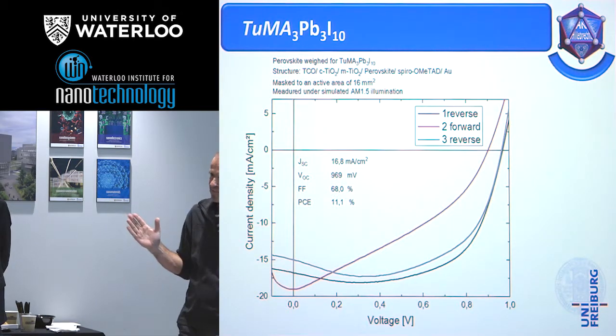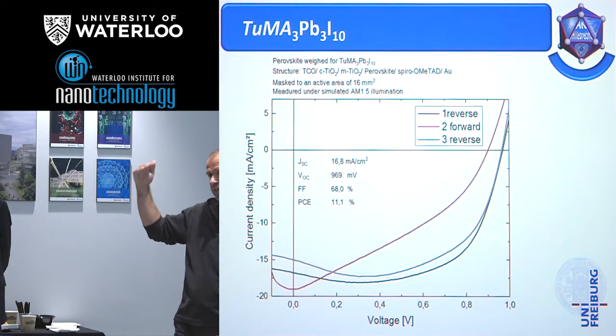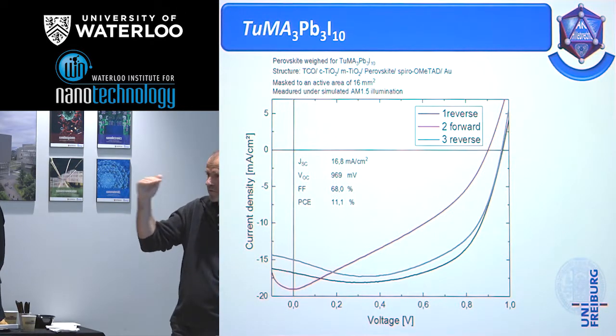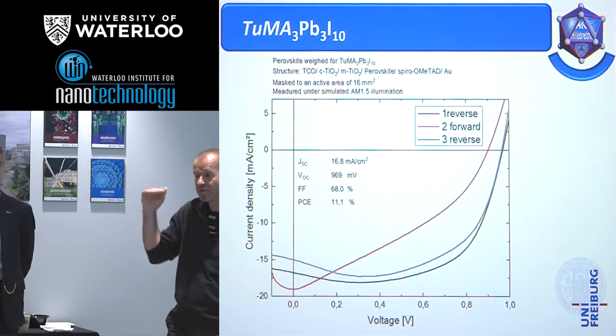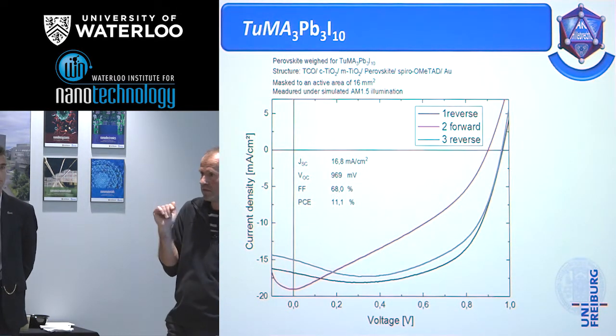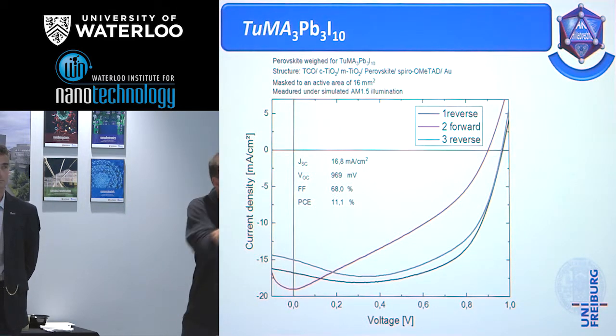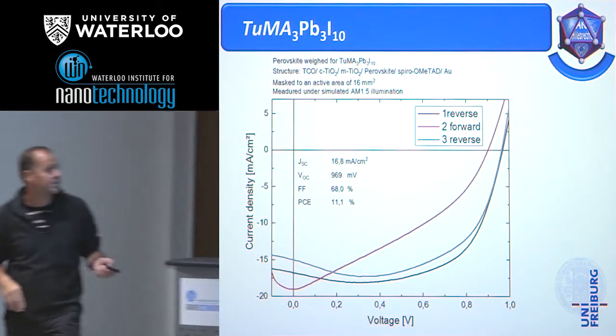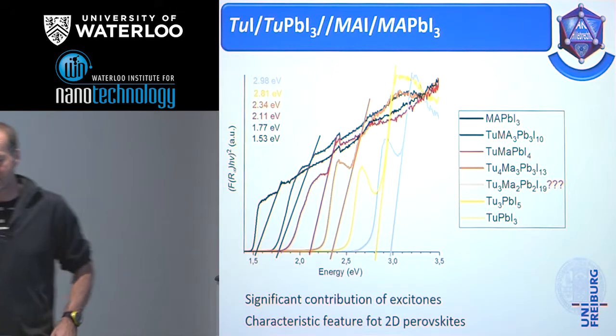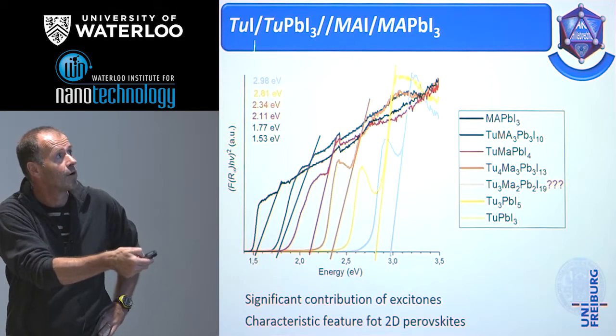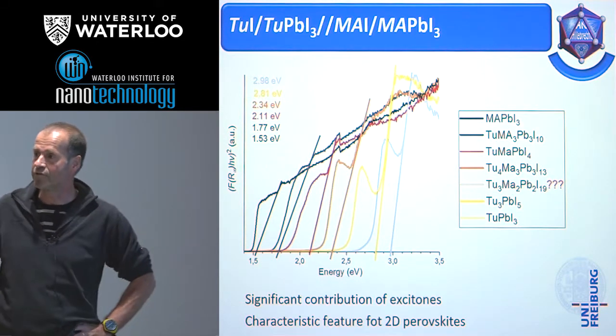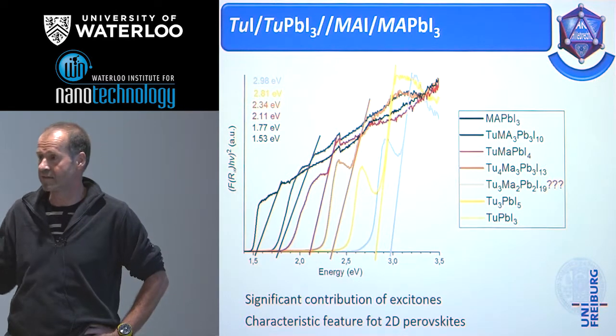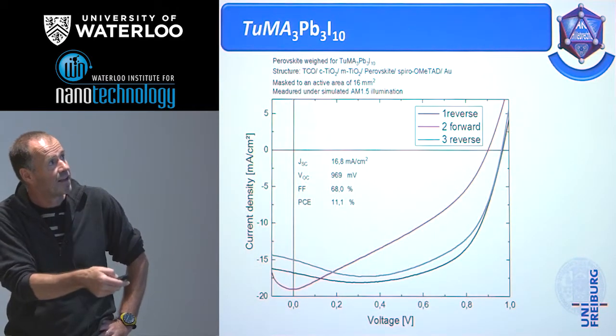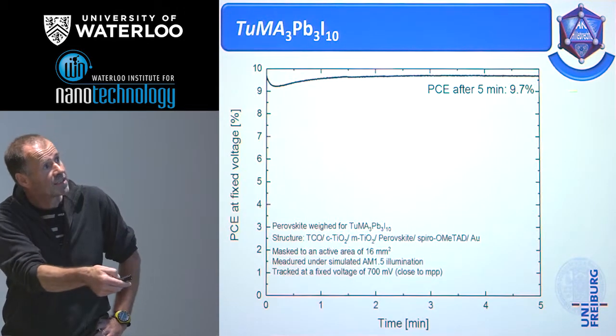That's impossible. But if you look at the process of the precipitation, then it has a strong influence on the kinetics. And that's why it is an influence on the microstructure of the layer of the methylammonium lead iodide, which is the same structure, same compound, but in a different morphology. So the influence is on the morphology, and that's why I was a little bit hesitating with these things here at the end. It is well known that with a slight addition of urea, you have a positive influence on the stability against hydrolysis. So I'm not sure that it is really this compound here which is responsible for these properties.